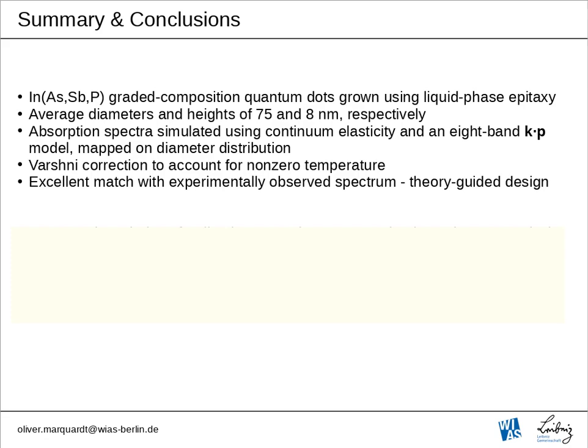So let me summarize my presentation. I have been talking about indium arsenide antimonide phosphide graded composition quantum dots today that were grown using liquid phase epitaxy. The average diameter of our systems was observed to be 75 nanometers with average heights of 8 nanometers, and we have simulated absorption spectra using continuum elasticity and an 8-band k.p model, and then mapped these energies after applying a Varshni correction on the diameter distribution observed in experiment. We found an excellent match with experimentally observed spectra, and that allows us to conclude that we can use this approach for theory-guided design to help experimentalists to look for specific systems.